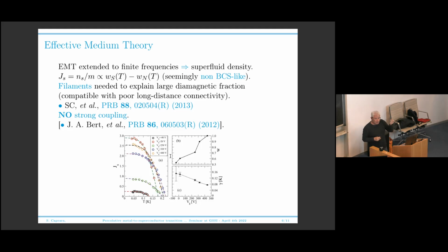But if you now measure the response of your system at a finite frequency, then there is an interesting response in the superconducting phase too. This response at low frequency is purely reactive. So the conductance is purely imaginary. The real part of the resistance is zero, but you have a purely imaginary conductance, which gives the reactive response of your superconducting cluster.